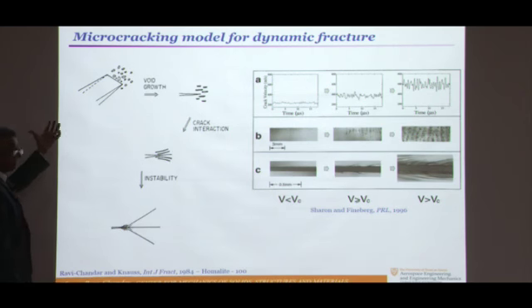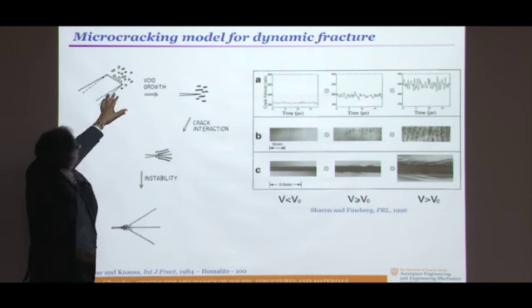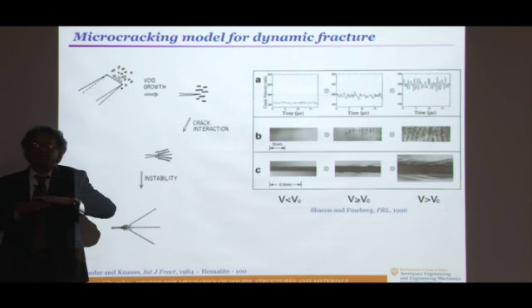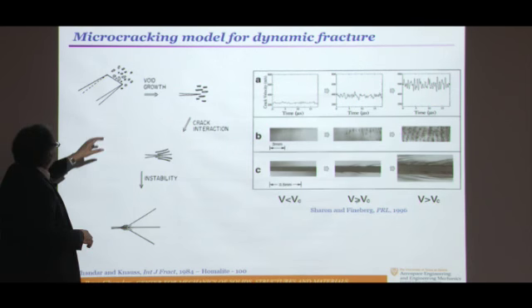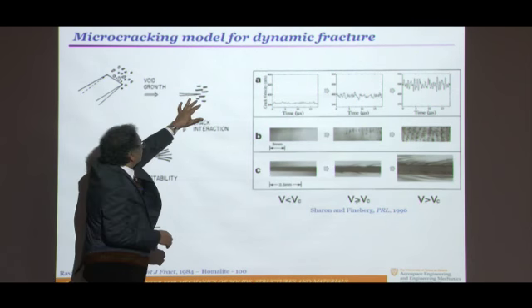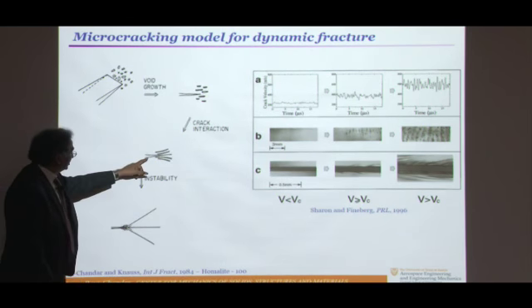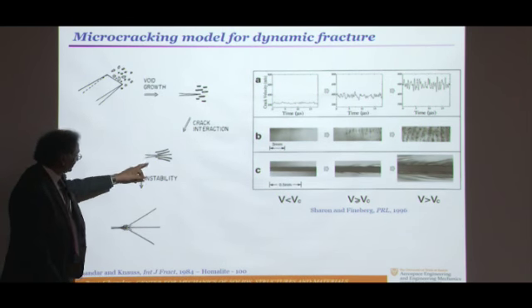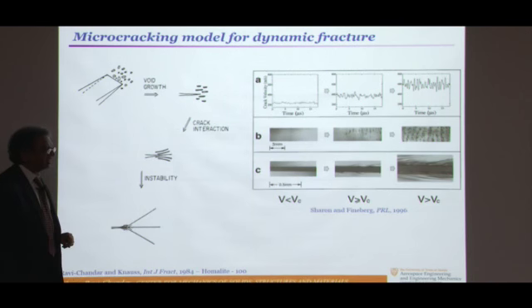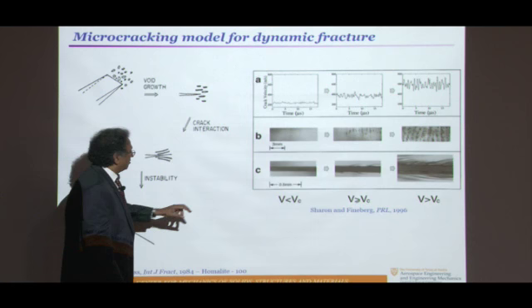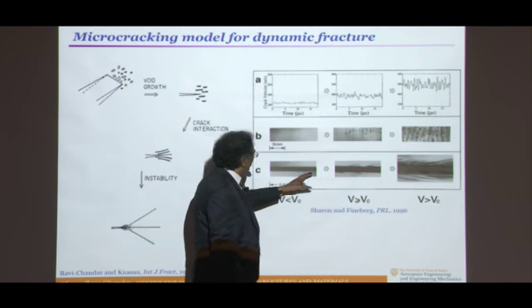The phase field will just control what happens in the crack surface and a very small fracture process layer. It doesn't change what happens to bulk plasticity. So you do the bulk plasticity the way you normally would, but account for dissipation in addition to the elastic dissipation of the surface energy. You need additional dissipation for plasticity.